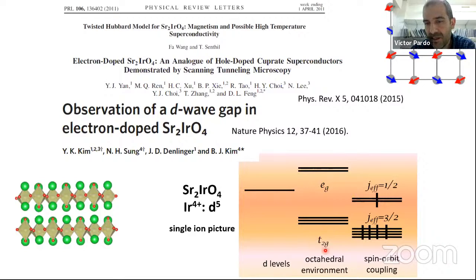Because the t2g manifold works as an L=1 subsystem, when you introduce a spin-orbit coupling, and iridium suffers a strong spin-orbit coupling, you have L+1/2 and L-1/2 manifolds, and you have one hole here in a J-effective 1/2 orbital. And this is similar to the spin-1/2 of the cuprates. So in principle, similar physics could be expected in these iridates.